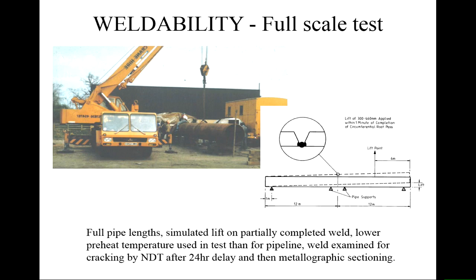So here's a full scale test in operation. This is to test the craning of a pipe that's been partially welded into a trench. So you've got a weld here and the root bead has been completed, but none of the capping passes or fill passes have been done. Then that weld is being picked up by this crane. The whole thing will be bent and stressed, and it will be moved and put down as if it was being craned into a trench.